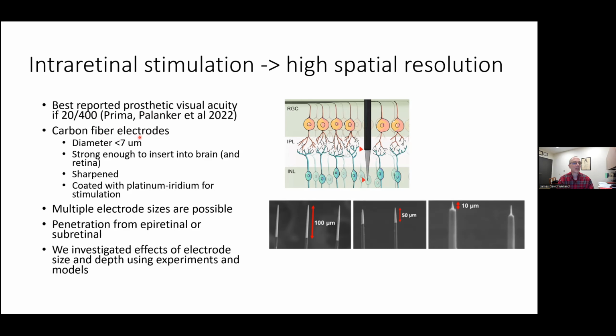So carbon fiber electrodes are a technical approach to that, and that's what's shown in both this diagram and these electron micrographs here. This is something my colleague at Michigan, Dr. Cindy Chestek, has advanced for neural recording. And then we deposit on our platinum iridium material. I also want to disclose I have a commercial interest in platinum iridium, so I'll talk about that a bit in the next few slides. This is because carbon itself is not robust for long-term electrical stimulation. So as you can see, we have a few design choices we can achieve with carbon fiber electrodes, including something as small as 10 microns, though the robustness of this is somewhat questionable if you try and insert something with a small tip like this.